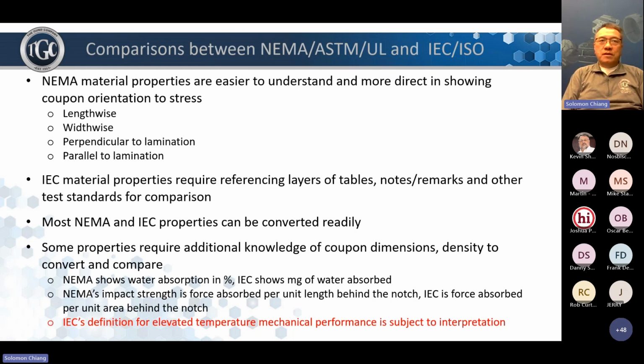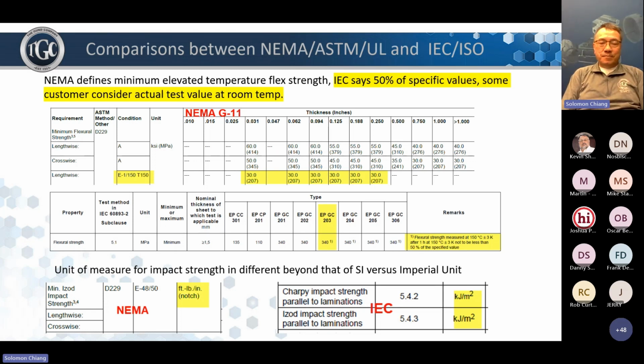It's like water absorption. NEMA and IEC use different philosophies in how they want to express water absorption. The same goes for impact. And then the one beef that we have is the IEC definition for elevated temperature mechanical properties. As you can see here, with NEMA, it's very clear. At room temperature, the flag is 60,000 psi, and at elevated temperature, it's 30,000. So roughly half. That's what IEC said.